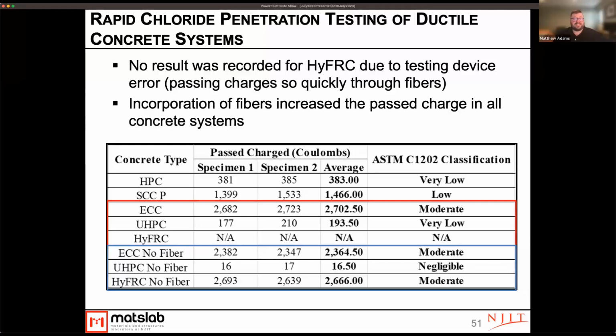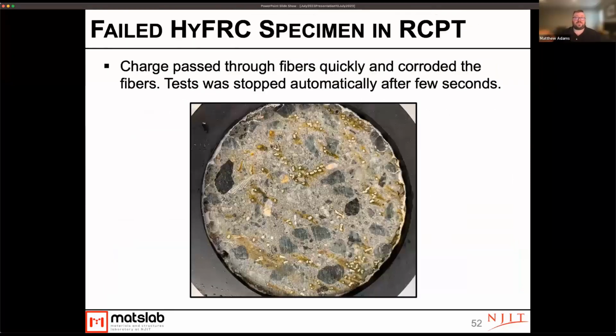However, both the ECC and HyFRC showed fairly high charges passed, above 2,000 coulombs, but that doesn't match really well with our profiling testing and our G109 testing. So it's pretty clear that the RCPT test is not really a great measure of chloride performance with these ductile concrete systems. So really more understanding to recalibrate that test method needs to be done.